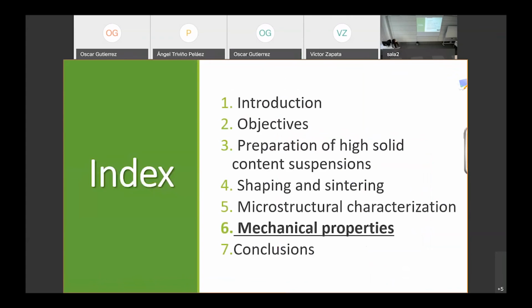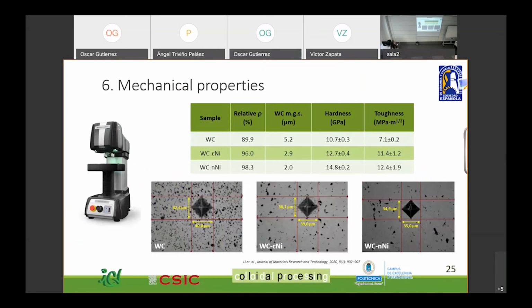So we carried out some mechanical property tests. In this case, we used indentation tests to measure both hardness and toughness for our materials. With 1 kilogram Vickers indentation, we measured hardness, which gave some remarkable results. In the case of tungsten carbide, we had a very low value of hardness, probably due to all this porosity, but it improves with the addition of nickel, especially, again, for the metallic nanonickel. And in the case of toughness, we did 10 kilogram indentation tests, and the results have the same tendency as in the case of hardness.